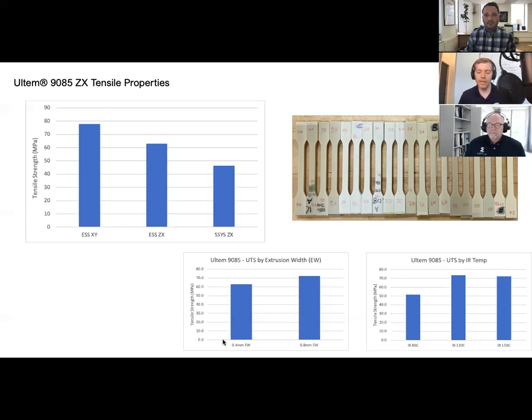But one thing we've seen with the HSC that's really interesting is that since we extrude at such a faster speed than other platforms on the market, it opens up new possibilities in terms of increasing your interlayer bonding. The degree to which 2 layers of material deposited onto each other bond and fully weld together has a lot to do with the thermal history. As I print faster and faster, I get closer to an isothermal process, which gives me a big boost in my mechanical properties between the layers.